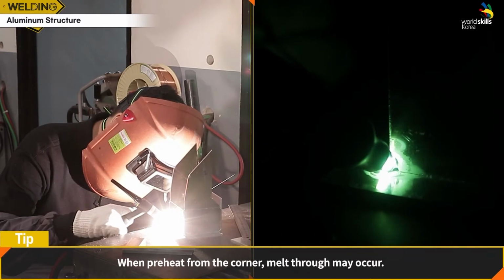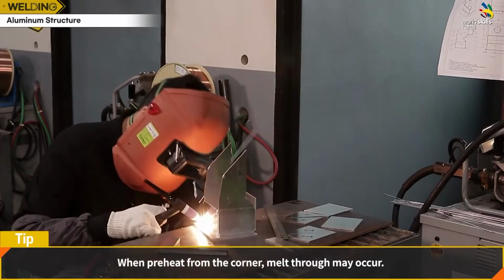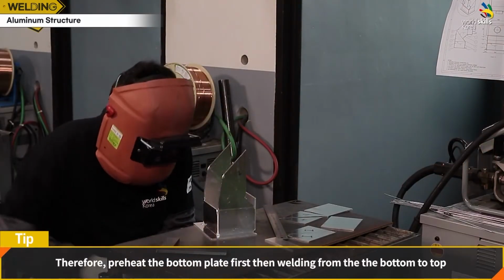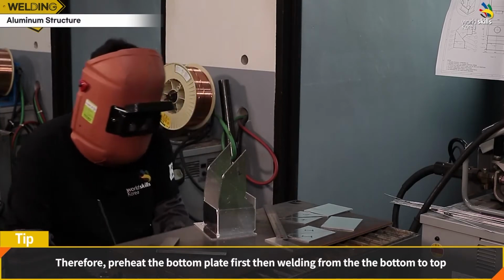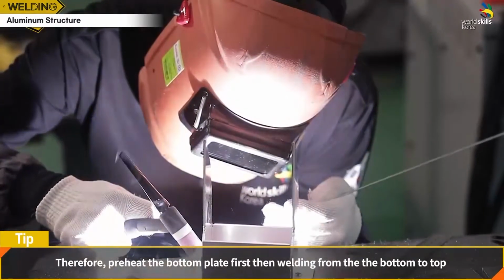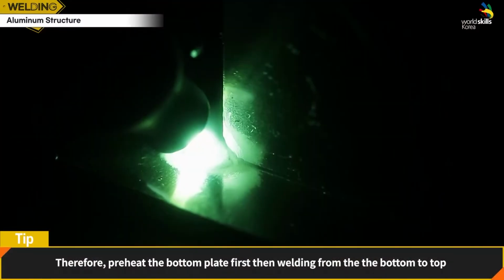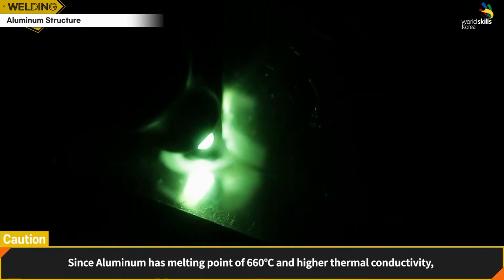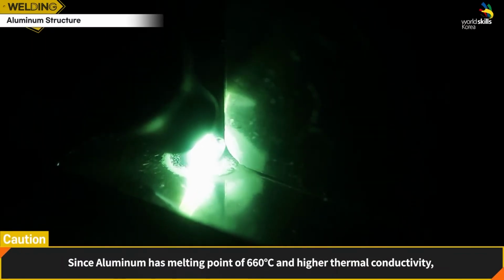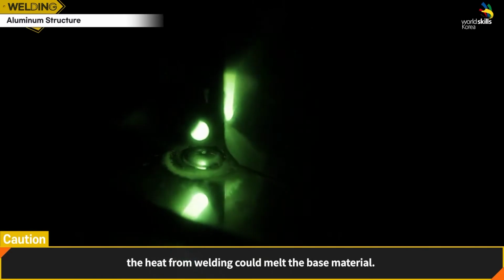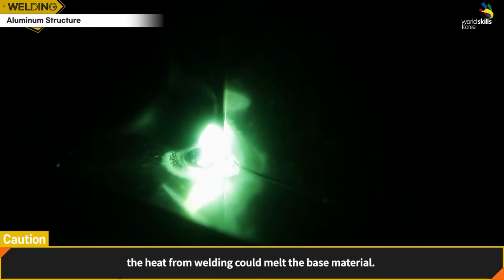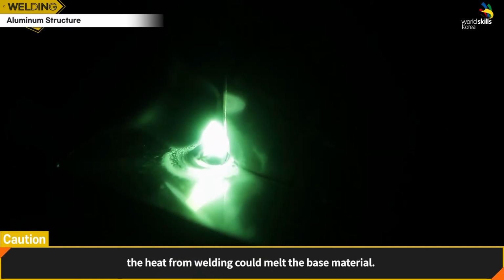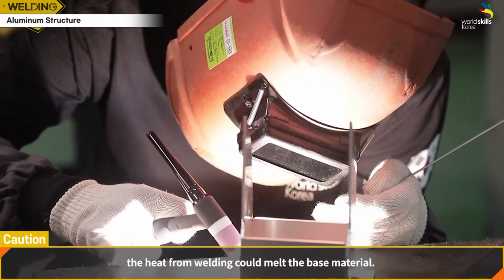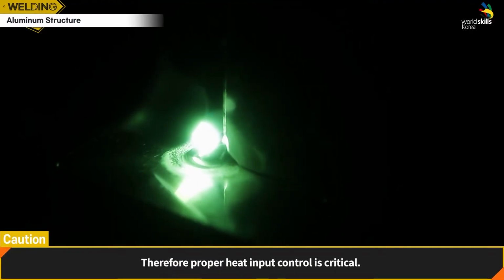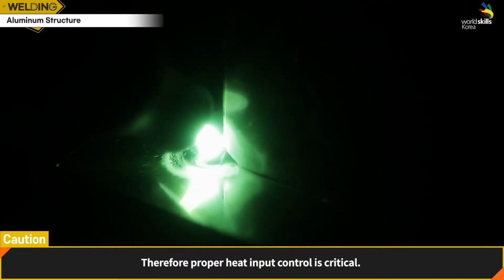When preheating from the corner, melt-through may occur. Therefore, preheat the bottom plate first, then weld from bottom to top. Since aluminum has a melting point of 660 degrees Celsius and higher thermal conductivity, the heat from welding could melt the base material. Therefore, proper heat input control is critical.